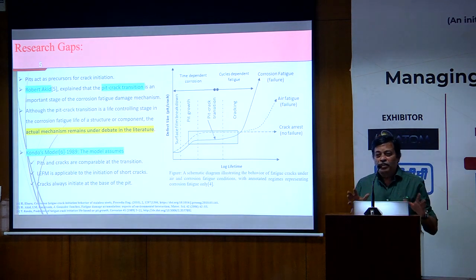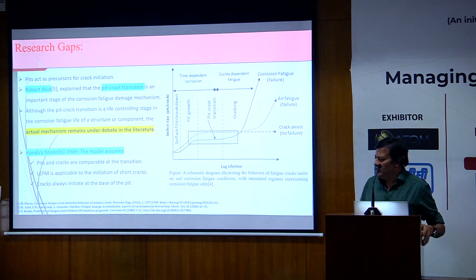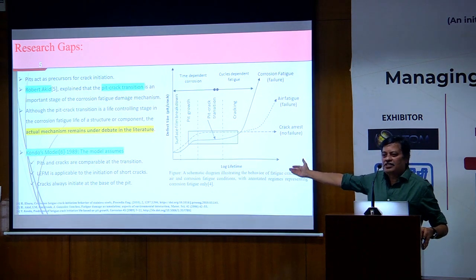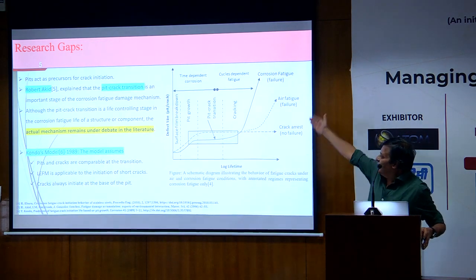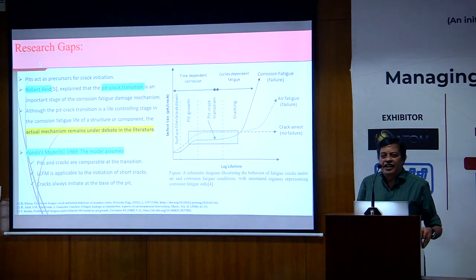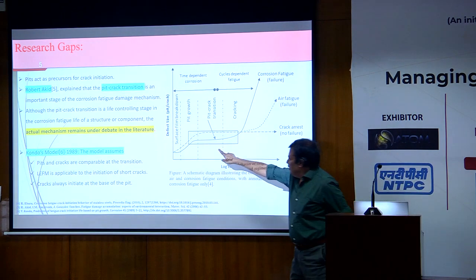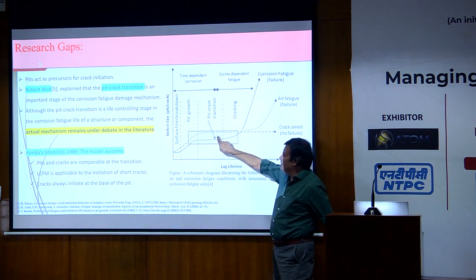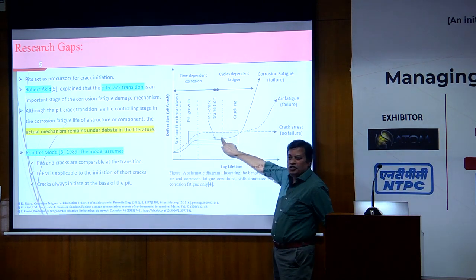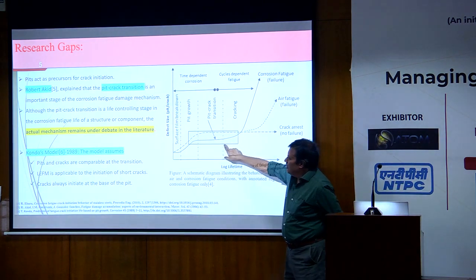The most important part is that after the pit grows to a certain level, it saturates, and then the pit will translate into a crack. And the cracking will happen under the action of fatigue. So this is a very important part that needs to be understood before the cracking takes place.